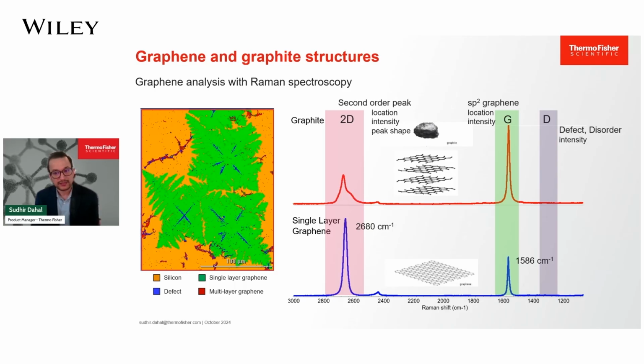On the left side of the slide, you'll see a Raman image of graphite electrode grown on a silicon substrate under experimental condition. This image was created using raw spectral data, such as those described earlier and shown on the right. The image can be used to visualize presence of single layer graphene, multiple layer graphene or graphite, defects, and the silicon substrate itself. Raman images like this are an extremely powerful tool in all stages of quality control, research, and product development.